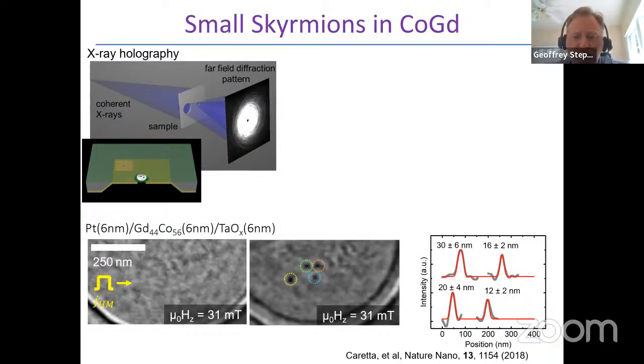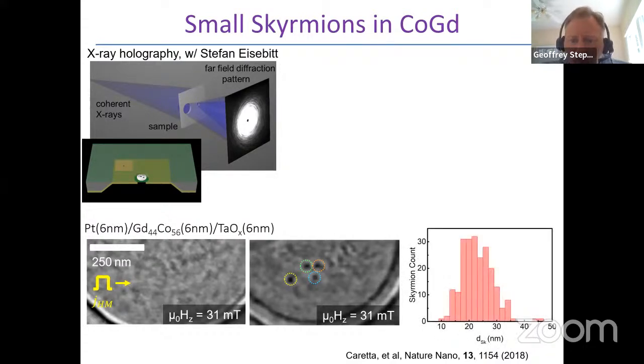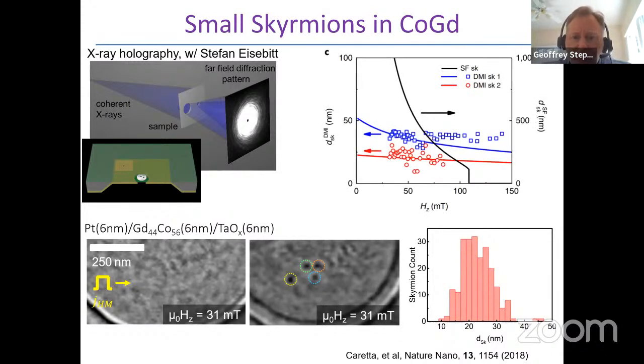There was a relatively large distribution of sizes in these materials, with a diameter averaging about 20 nanometers. And these at the time were the smallest skyrmions that had been seen in a material. And again, they have been seen to be stable both at room temperature for reasonably long times and under large magnetic fields.